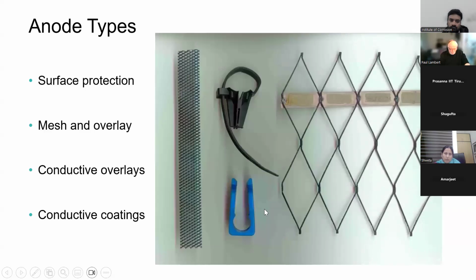Reinforced concrete. I'll just show you very quickly. I don't want to overrun, but I think just for completion, I'll show you a few systems. A lot of systems have been developed now for use in reinforced concrete, thereby combining both the OPC and the PC. We have meshes and ribbons. These are made from coated titanium, mixed metal oxide titanium. The mixed metal oxide stops the titanium from anodizing. If we didn't put it on, the titanium would pass current very briefly, but then it would protect itself with an oxide layer, much as aluminium does.